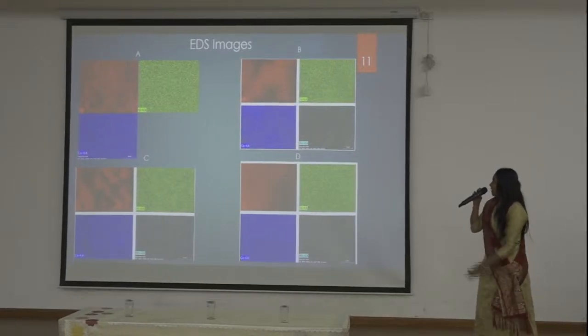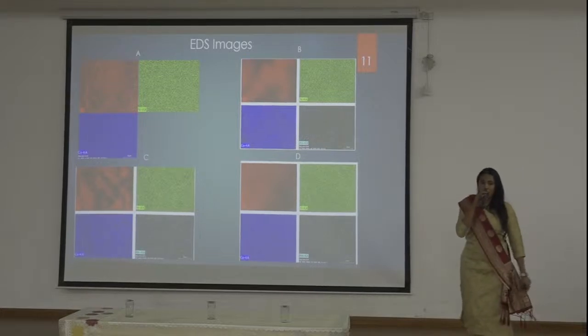Okay, so this is the EDAX images of the material. A represents pure nickel cobalt oxide, and B, C, D represent 0.01, 0.05, and 0.1 molarity ratio of manganese doped nickel cobalt oxide.